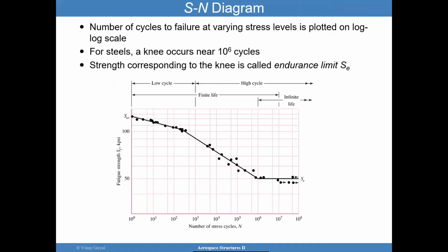For steel, a knee usually occurs at about 10 to the 6 cycles, and the strength that corresponds to that knee, we usually call the endurance limit, or SE. So here in this case, 50 KSI could be considered that. And so I'll call this low cycle fatigue typically. There's a small knee here, and then from here on you have high cycle fatigue. Typically low cycle fatigue goes up to 1,000 cycles.